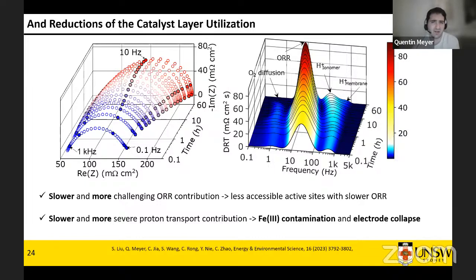Now, looking at our ORR, again, there are multiple ways to look at it. So the first one is we have our particles, roughly some sort of hexagonal particles, and you have the active sites inside the particle and outside the particle. So maybe initially we use up the active sites that are outside the particle, very easy to reach. That's why there's quite low resistance, quite a fast phenomenon. And then as you degrade, you have to go deeper and deeper and deeper into the particle.